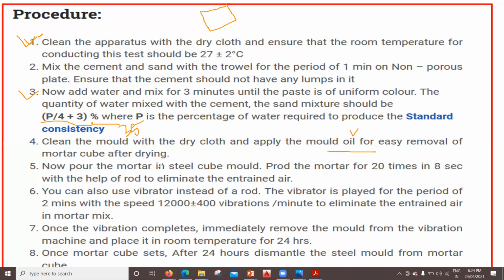Next is now pour the mortar in the steel cube mold. Pour the mortar for 20 times with 8 seconds with the help of a rod to eliminate the entrained air. So this is not required again. So you just have to pour the mortar in the steel cube, and when you are pouring it, you have to give a tamping to that so that the cement paste will go everywhere and there won't be any void in that. Next, we can also use the vibrator instead of a rod.